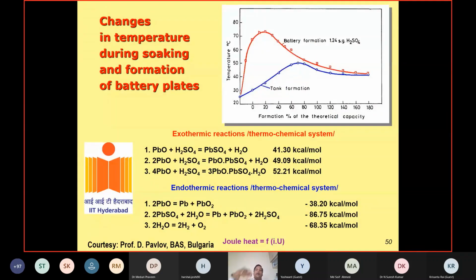One important thing: once you put the electrolyte, 1.25 or 1.26 or 1.24 specific gravity sulfuric acid, as soon as you put sulfuric acid, a lot of heat is evolved at the positive and negative electrode. I told you the temperature should not go beyond 65 degrees centigrade. So what they do is put the cells in water, because if the temperature goes above 60 or 65 degrees centigrade, there is a possibility of a change in active material to a different composition. So that's also very important.